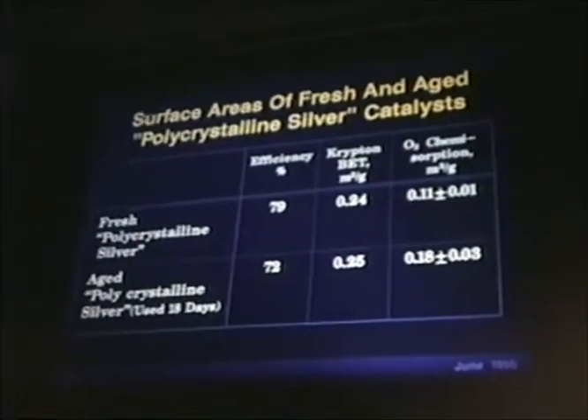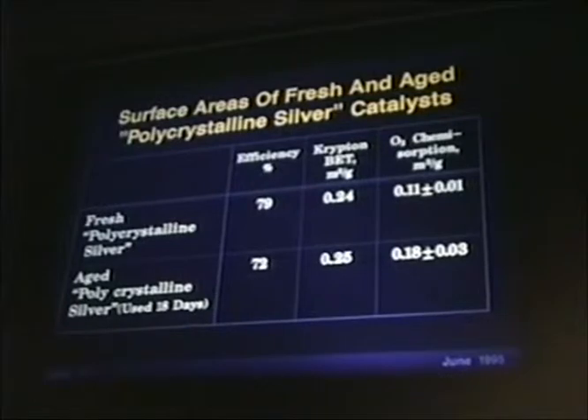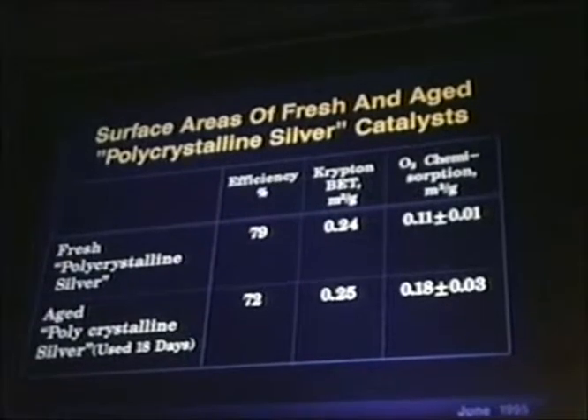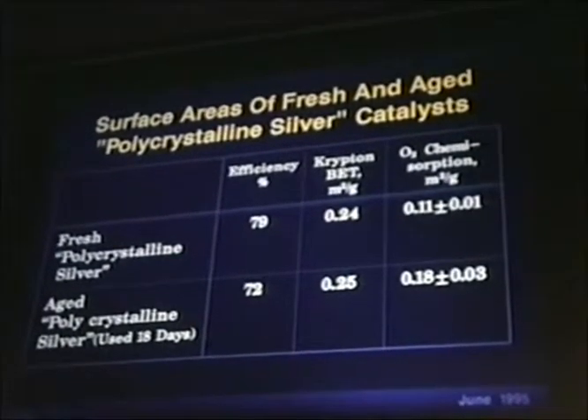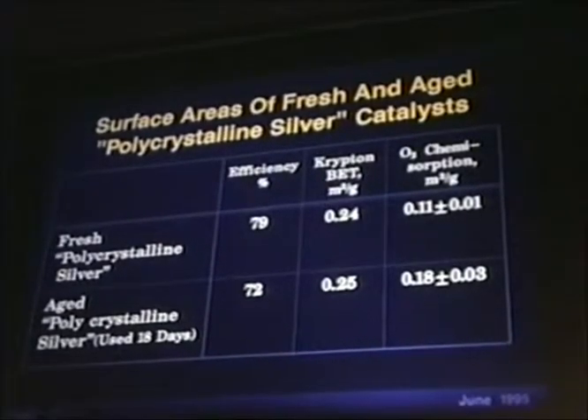A high purity polycrystalline silver catalyst containing a small amount of sodium was found to lose substantial activity and efficiency in only 18 to 19 days of operation. As I mentioned, this catalyst is pure silver and hence contained no support. The sodium promoter was responsible for its initial high efficiency of 75% to 80% at about 5% to 10% conversion.